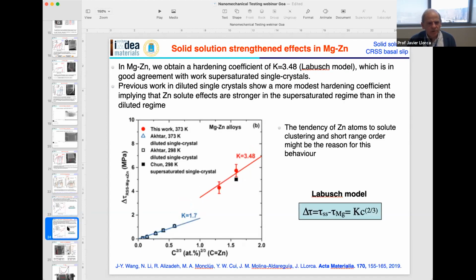These are the results for solid solution strengthening effects in magnesium zinc alloys. In this particular case, the amount of data in the literature is extremely limited. These are the only data in the literature, and again correspond to some work by Akhtar 30 or 40 years ago. This is some more recent work on a supersaturated single crystal. And again, these red points are our experimental data. Of course, our experimental data using micropillar compression are in agreement with other data using standard single crystals.